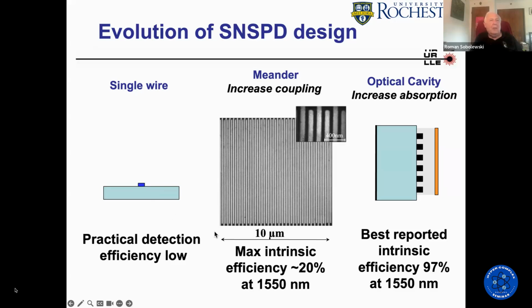So the first step was to make an extensive meander. You can see the black is the niobium nitride, and it's 10 by 10 microns, and you can see here this is very extended. So that meander is on the order of a millimeter. And then we have a large enough area that we can well focus even an infrared beam like 1.5 micron. This way we can get much higher efficiency, and that efficiency would range up to 20 to 30%.